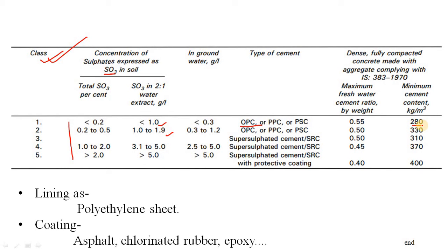If more sulphate is there in the soil or the water, in that case you may have to use polythene sheet as a lining - that means first spread the polythene sheet on the ground then start your casting. Either you may also use asphalt coating or epoxy coating in the member to save your concrete from this sulphate attacking component.